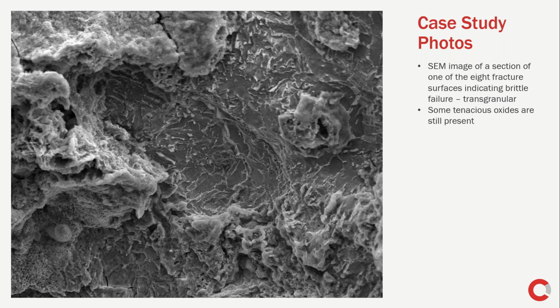The platform was made of carbon steel, which is the most common steel that one can encounter. This carbon steel, when it's subjected to stress, usually fails in a ductile manner. It means that it has some plastic deformation, some yielding before the final fracture. However, in this particular instance, when I looked at the fracture surface under higher magnification, I saw typical features that are associated with brittle failure. What it means is there was no deformation. The fracture was like a glass fracture. It was all of a sudden, without any plastic deformation.